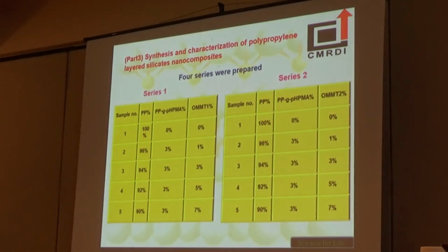The third part of our experimental work was the synthesis and characterization of polypropylene layer silicate nanocomposites, in which 4 series were prepared using the 2 different organically modified clays. Within the first 2 series, the amount of added organically modified clay is varied from 1 up to 7 weight percent, while the amount of added compatibilizer remains fixed all over the experiments. The other 2 series are the same but in absence of a compatibilizer.